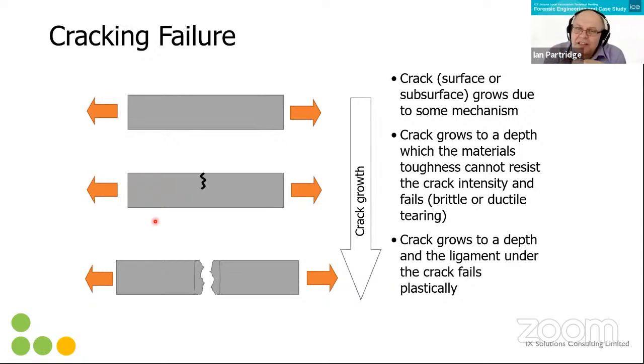Cracking is another issue. So you get a crack, either on the surface or subsurface, growing due to some mechanism. It may be stress corrosion or fatigue or creep. And this crack grows to a depth when the material's toughness cannot resist it. It can't resist the intensity of the crack tip anymore. And it fails either brittly due to it being a brittle material, or you get ductile tearing due to the material having a good level of toughness.